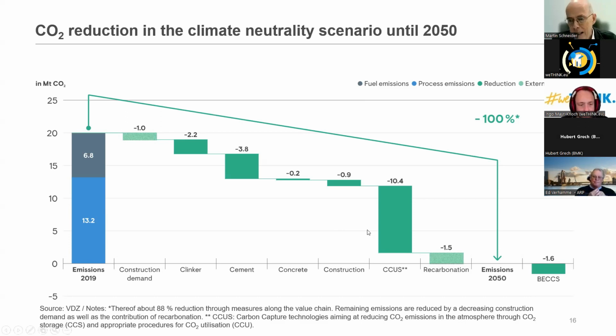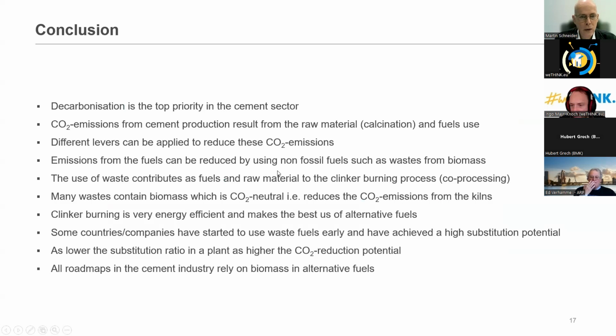So that means there's a contribution of the carbon capture process to lower the overall concentration in the atmosphere. And we need this here because the whole value chain is, of course, theoretically 100%. But if you go to a single plant, it's not really 100%. The availability of the capture devices is 90 to 95%. So there's always a need to capture this remaining part.